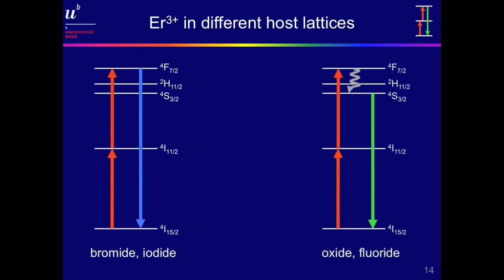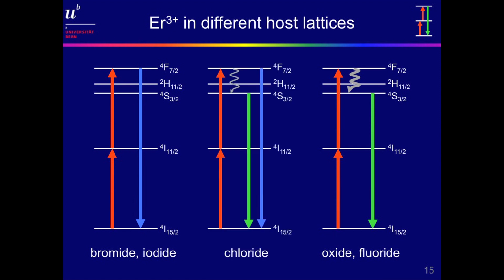In an oxide or fluoride, however, phonon energies are bigger. Multiphonon relaxation is more efficient, and the system relaxes to quartet S 3/2 before it luminesces green. Chlorides, finally, are somewhere in between. Some are blue, some are green. The example we've seen just before was a green one.